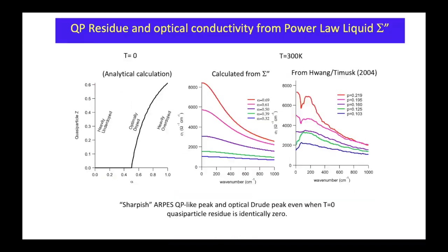Okay, so with this, we can also calculate optical conductivity. This is done at 300 Kelvin. So this is sigma 1 versus wave number, at 300 Kelvin for different dopings. Here, it looks like there are some Drude-like peaks, but they're not real quasiparticles. It's not from a liquid. And compared to experimental measurements of the same, again with the same scales, 2,000 and 8,000, etc., and the doping levels.